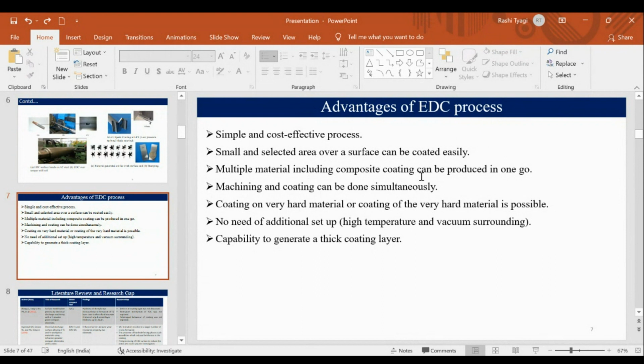Multiple material, including composite coating, can be produced in one go. It means there are different materials that you can use at one time. You can do the composite coating. You can use titanium carbide powder and titanium nitride powder combined, and then produce that coating. So multiple materials can be used, and machining and coating can be done simultaneously. Sometimes, when we are doing the machining, the recast layer contains a lot of cracks, as I already discussed. In machining, the recast layer forms that contains cracks and porosity.